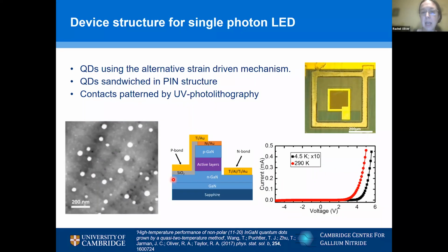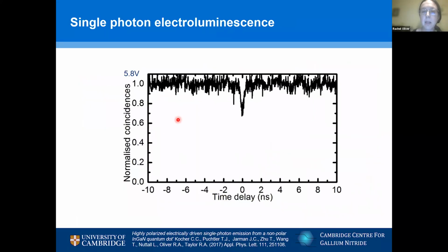A little bit of extra care has to be taken in the processing to make the contacts, to make the device survivable for the low temperatures. But we have diodes, and although we increase the turn-on voltage, we see that they do operate as diodes at even down to 4.5 Kelvin. This is my first single photon electroluminescence trace from such a device.